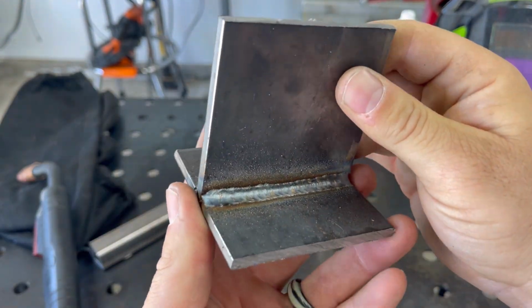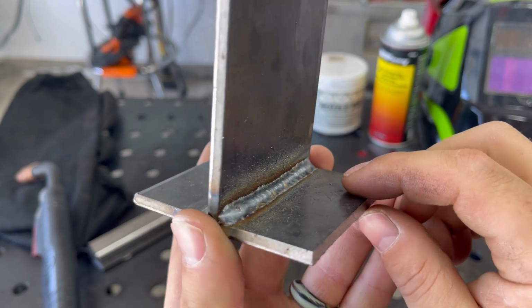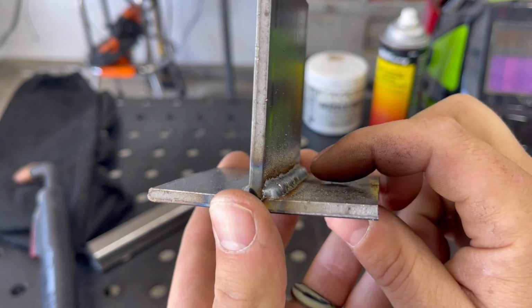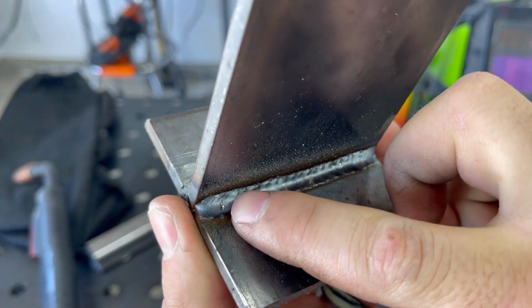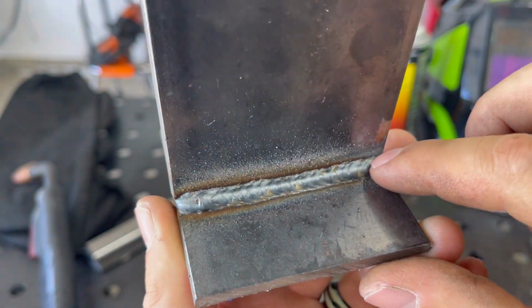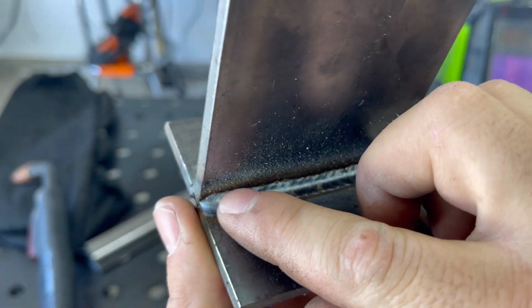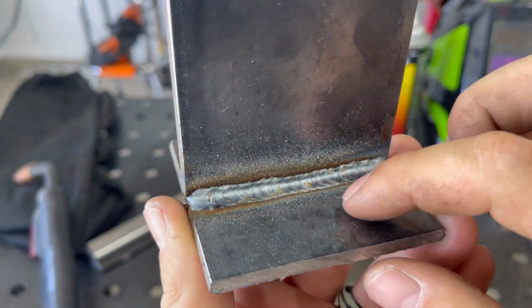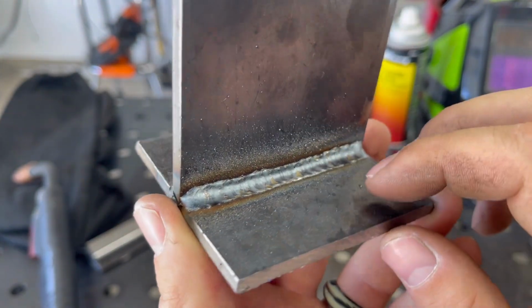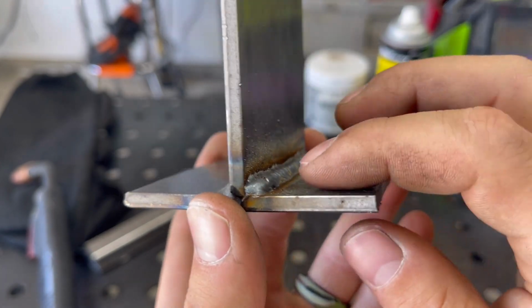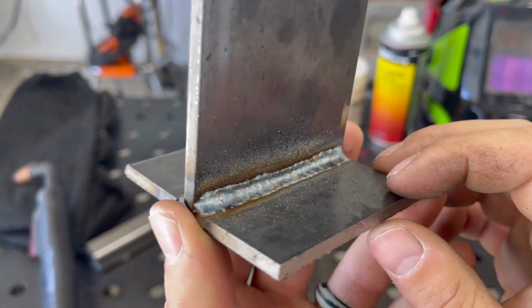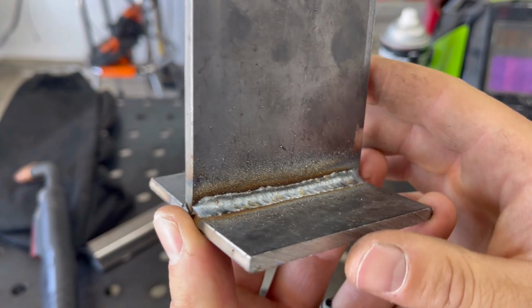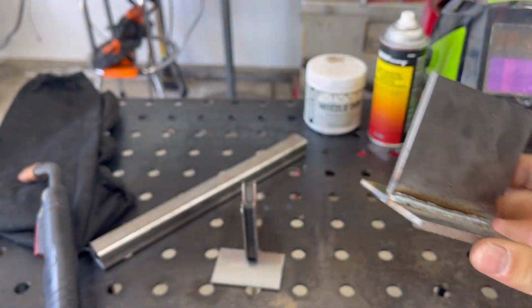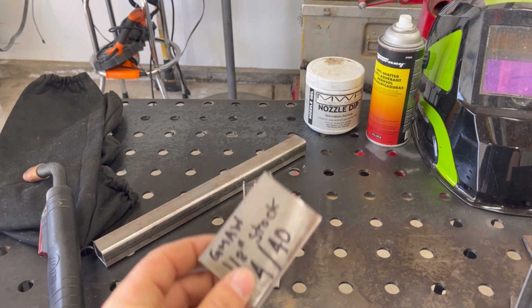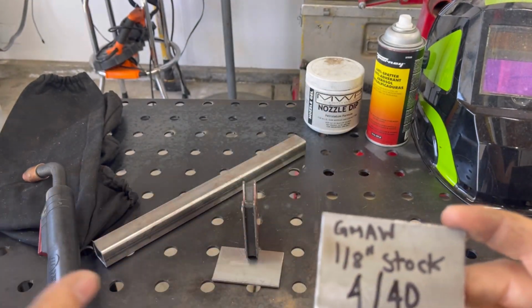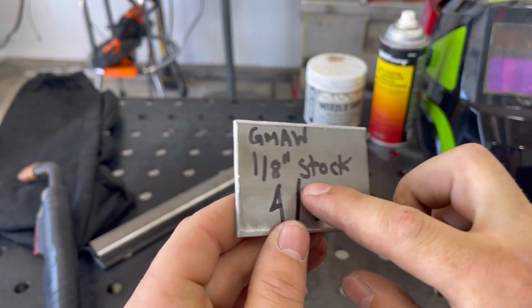So I've already done a weld with the 3/16 inch stock, and as you can see, the weld is more convex. The width is good, but as you can see, it's not washing in well to both sides of the material, bridging the gap. And this would be considered more like a cold weld where there's not a lot of penetration here. So that's the effect of welding on thicker material outside of the maximum limitations of the welder. So now we're going to step it down to 1/8 inch.